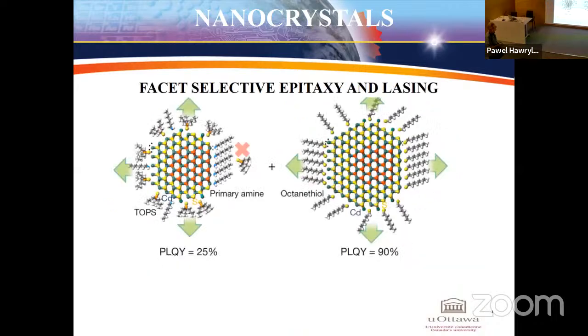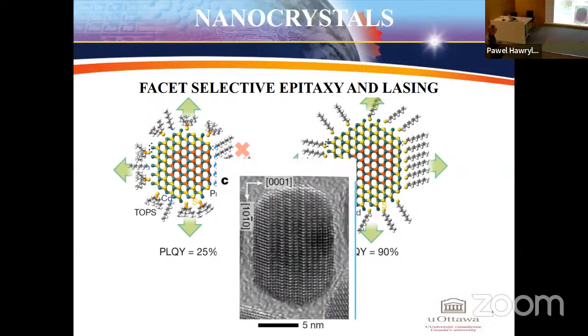So this is a picture of these nanocrystals after facet-selective epitaxy. You see some facets are enhanced versus others. And in addition, there is chemistry going on with different molecules passivating the structure, and you go from quantum efficiency of 25% to 90%. So this is how this facet-selective epitaxy looks.